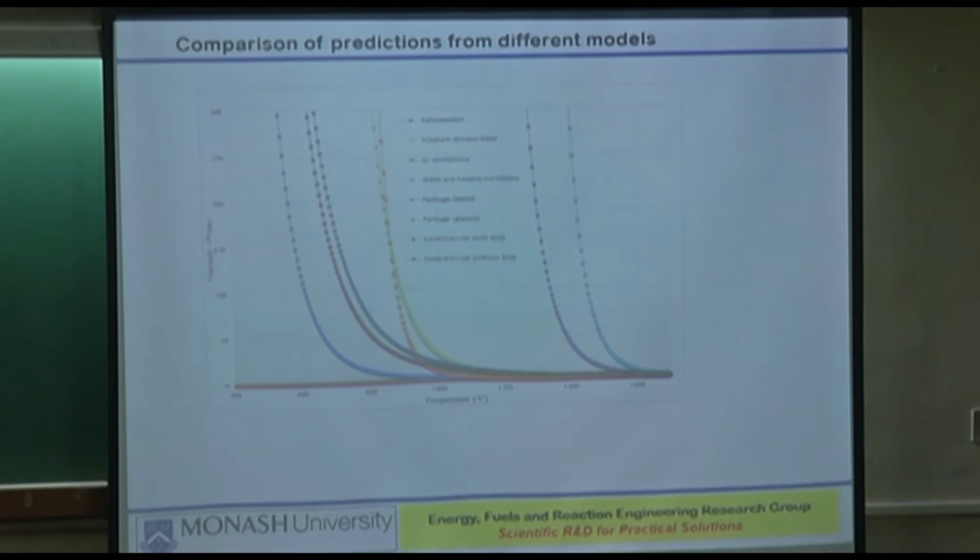So during the measurements, we made a careful decision. Okay, we cannot put hydrogen because these experiments will take a very long time. Not only will we have to melt them, but we will have to make sure that they melt fully, which is a function of time. And we don't know how long it will take to melt. It could take 8–10 hours to melt, and literally they do take 8–10 hours to melt, and we found it out the wrong way, through a difficult exercise.